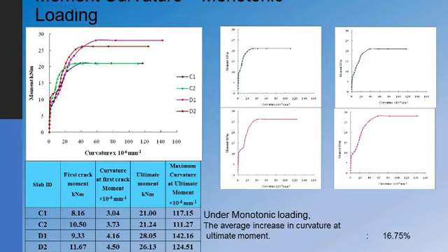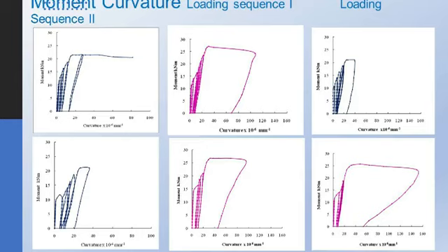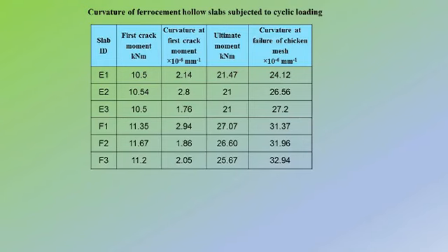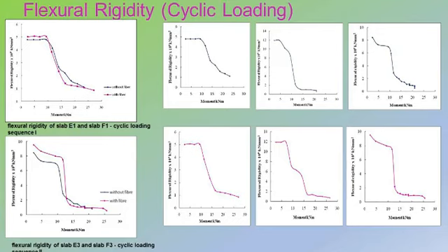So this is the moment curvature behavior for monotonic loading. Here the average increase in curvature at ultimate moment was 16.75%. And this is the moment curvature behavior for cyclic loading. Here also we have the readings: first crack moment, curvature, then ultimate moment, and curvature at failure of chicken mesh. So these are the flexural rigidity curves.